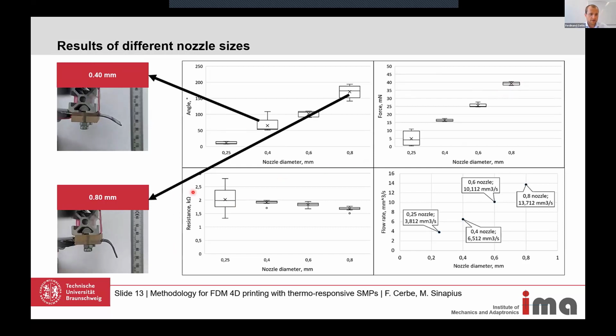Lastly, we have the resistance here, which lies somewhere around 1.5 to 2 kilo ohms, and the 0.8 millimeter nozzle also showed the lowest resistance in our case, which is beneficial because then we can apply a lower voltage, and therefore the risk of any hazard is reduced. On the bottom right, you can see that we also derived the flow rate during printing, which we thought might be an indicator for the transformation angle that we can see here.